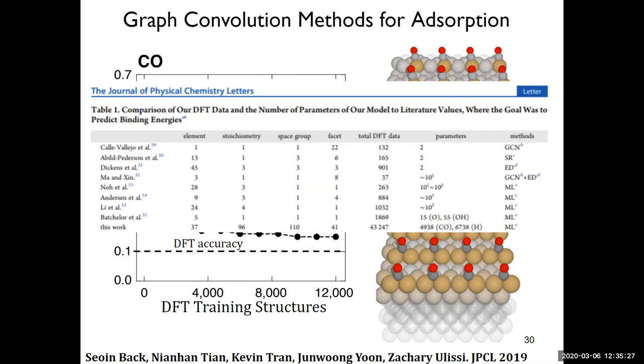So this was a table from the paper. We tried to find all the ones from the past 5 years that we could, different people doing different structure property relationships. Most of these are in the 100 to 900 calculation data set range. And these are PhD students sitting down and doing a bunch of calculations on different metal surfaces, not automated high throughput. This one is all single element compositions, so large, but not particularly diverse. Ours was another factor of 40 over those.